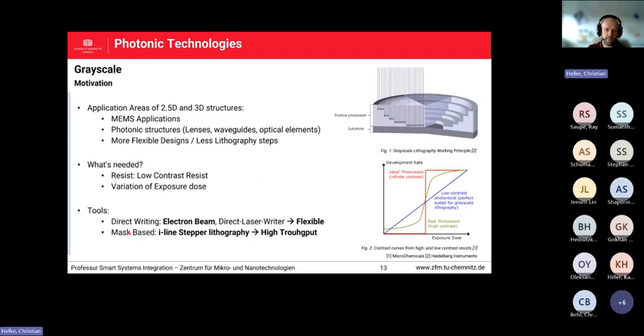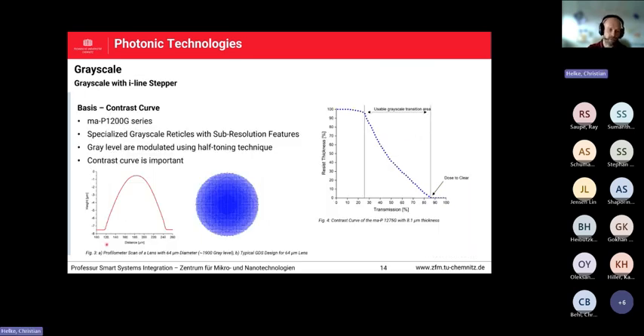So one can also think about mask-based systems, meaning here we are dealing with I-line stepper lithography, where you need a mask. And here the key element is the resist, the process itself, but also the mask, because the mask acts here as a modulation layer, meaning that within the mask you have the openings not just in the chromium layer as 0 or 1, but you have the layout you want to expose. It's more or less like a transmittance structure, and so this acts as a dose modulation layer, so that you can also tune the dose, even in the case that you have just one fixed dose per exposure within the I-line tool itself. And how does it look, for example? So here is a lens consisting of 64 micrometer in diameter and 8 micrometer height. It looks like this one.